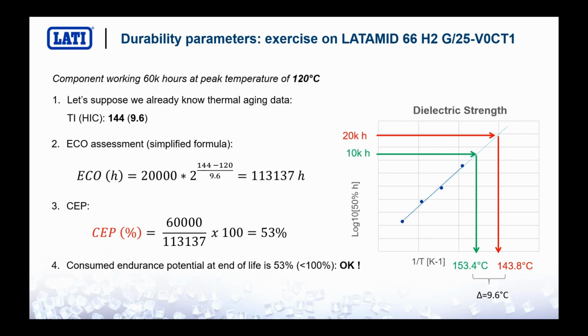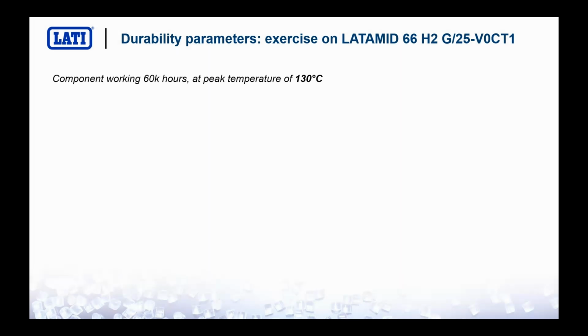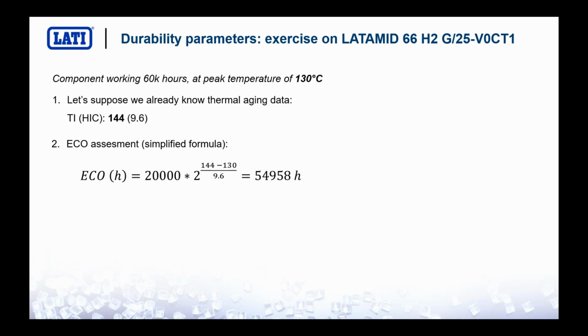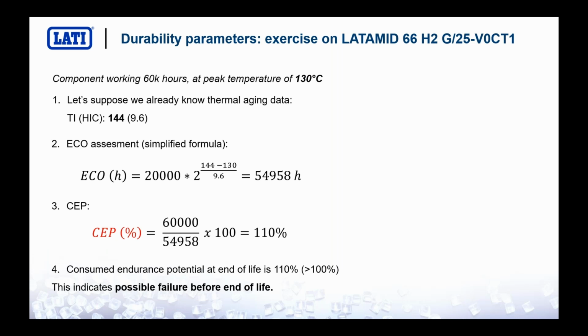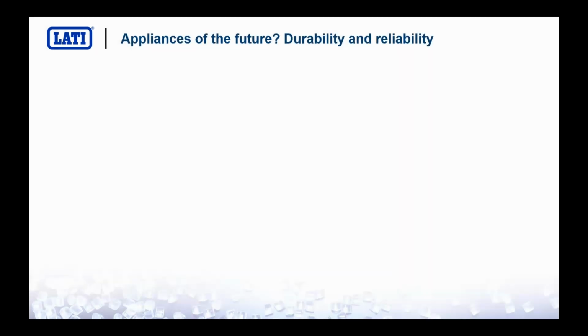On the contrary, let's suppose that we want to make the same exercise with 130 degrees C. What we evaluate is that with 130 degrees C, the amount of hours that the material can last is below 60,000 hours. So at the end of the 60,000 hours, this application is very likely to fail before the end of our time. And we are just talking about a difference of 10 degrees C. So you understand how important it is to have thermal indexes carefully evaluated and provided to customers.